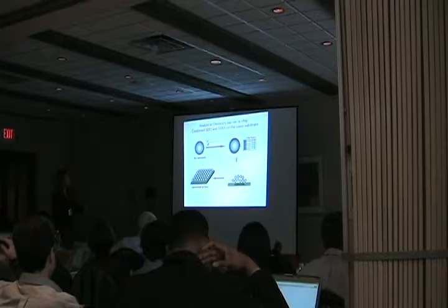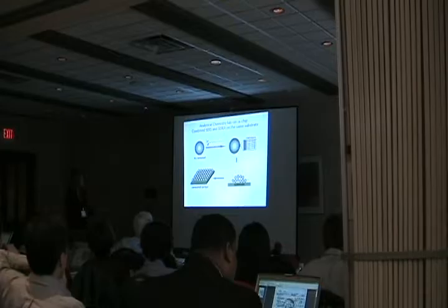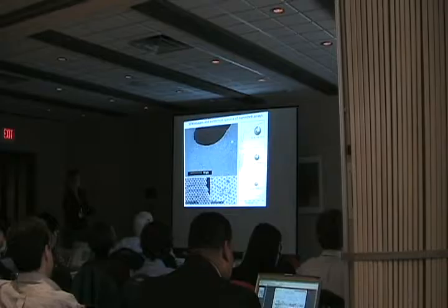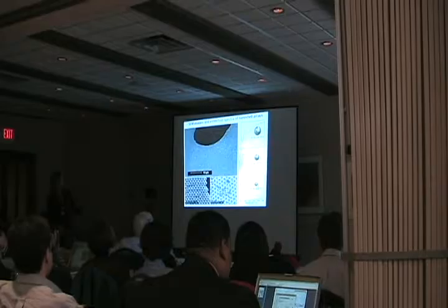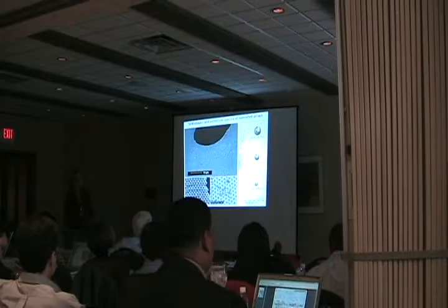We took a nanoshell coated with a surfactant and then made these very nice ordered arrays. The surfactant is essential because it provides a spacing of less than 10 nanometers between each particle. So we have a hotspot designed into these nanostructured arrays. They have the right structure in the mesoscale, and then they also have this long periodicity as shown here. And if we just look at the experimental spectrum, we have a single particle spectrum here, and then these are the array spectrum. So there's a very large, very broad mid-IR resonance that begins to form as soon as we take that same particle and extend it into an array.